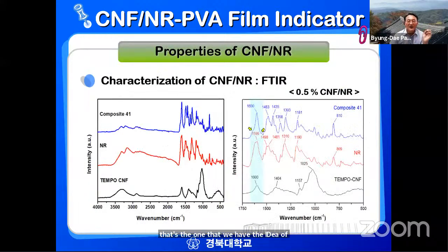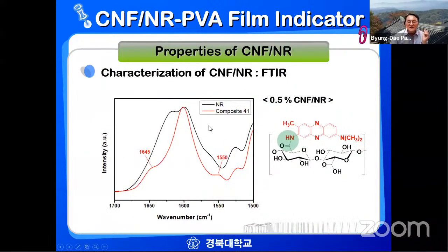And then we took the FTIR. This is the composite, and this is the TEMPO CNF and the neutral red. We check a slightly enlarged spectrum right here. There is a change at about 1600 wave numbers. As you see here, the neutral red is the control, and the red is the composite material. They have different peaks here, which belong to the amide group between nanocellulose and neutral red. So this confirms that there is a reaction between them.